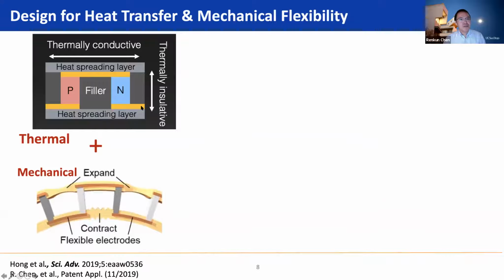And also, we want to match the heat transfer condition from the hot side, for example, on the top here, to the air. So we actually create this device with a specific design, thermal resistance between the hot side and cold side. We actually wanted to have a fairly insulative condition between the hot side and cold side. On the other hand, we also want to have heat spreading along the lateral direction within this elastomer, which is essentially a piece of polymer, but we want to increase the heat transfer laterally for better heat spreading. So these are the design conditions and goals.